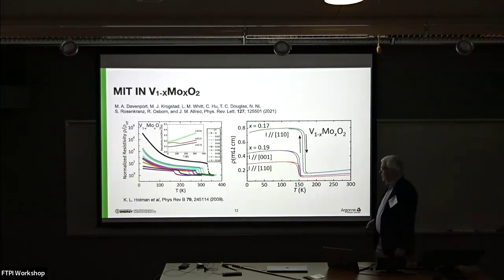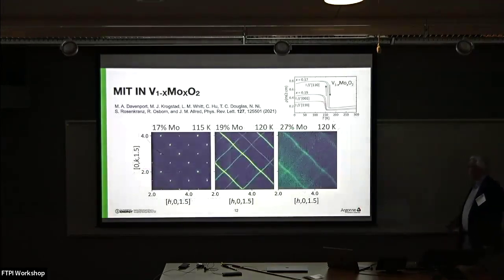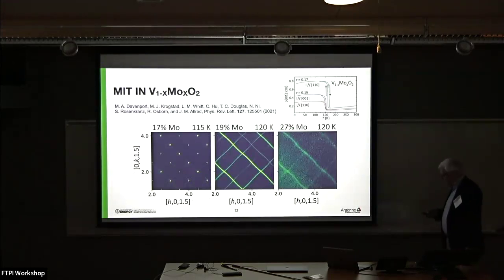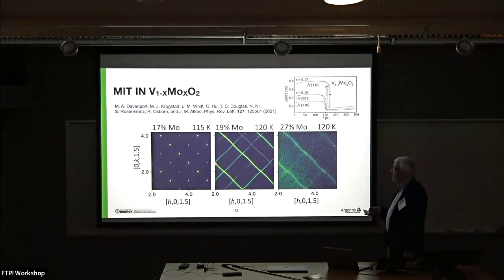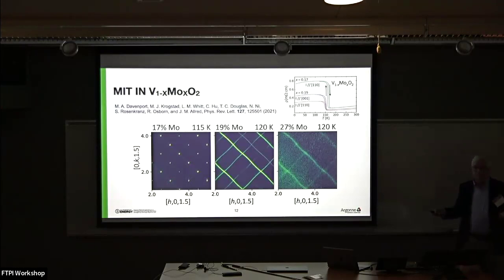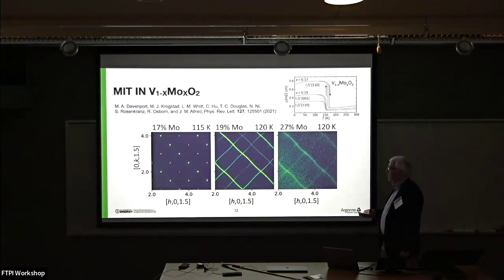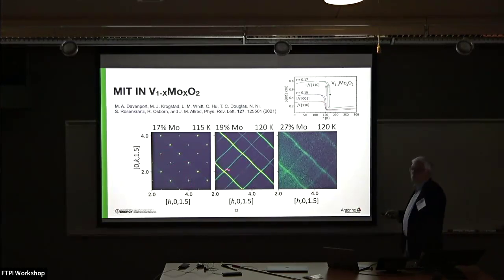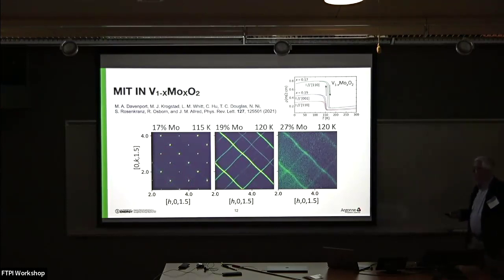What's happening structurally in this material? Well, it turns out that you get something rather more dramatic. This is the 17%, and here you see superlattice peaks, which are characteristic of the M1 phase. So the bright peaks are the long range order, that are forbidden by the pure rutile structure. As we go up to 19%, but remind you, you still have a first order electronic phase transition here, you've no more bright peaks. You just have these rather wavy rods. Keep on doping and they become increasingly diffuse.